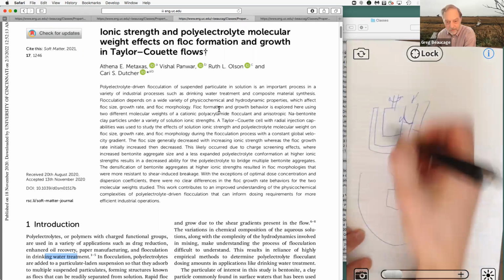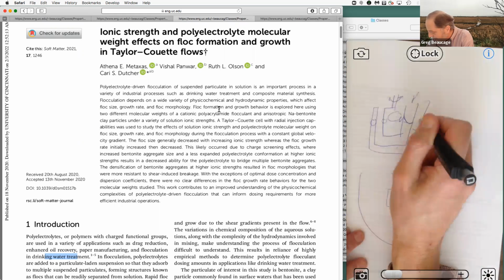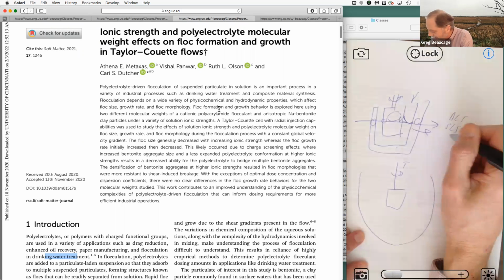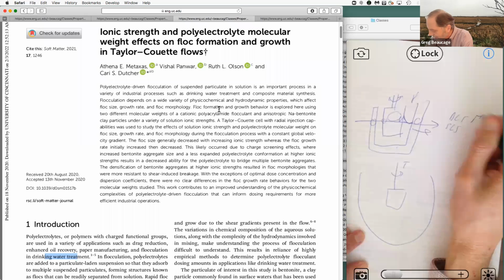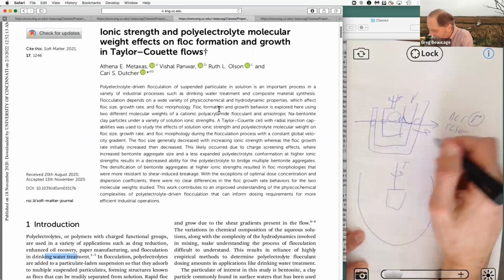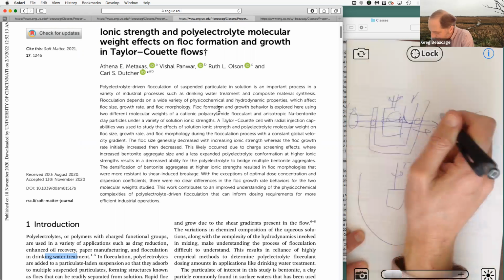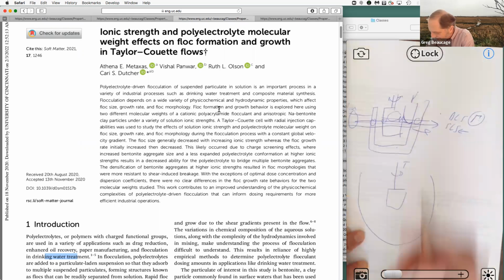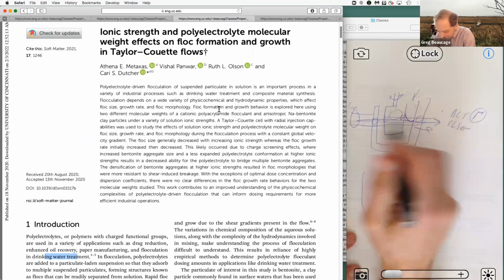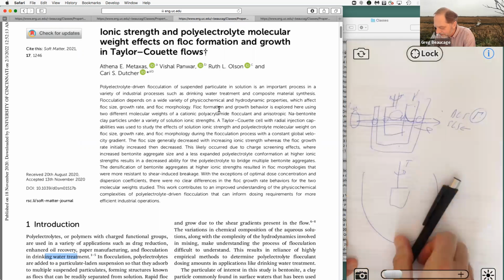The nice thing is, if you want to do light scattering through this, you can get a quartz bob with a quartz window and shoot the beam right through it and get dynamic light scattering, static light scattering. So we can get this gamma thing, the time dependence for the diffusion. You can get the structure, like how many flocs cluster onto a polyelectrolyte. And if you have a big one, you can put a 1 centimeter beam of neutrons through it and look at the structure, or you can shoot an X-ray beam through it if you use beryllium windows. So this cup and bob viscometer is popular for optical measurements, even though it's not ideal for the geometry for flow. You can shoot a beam right through it, right?